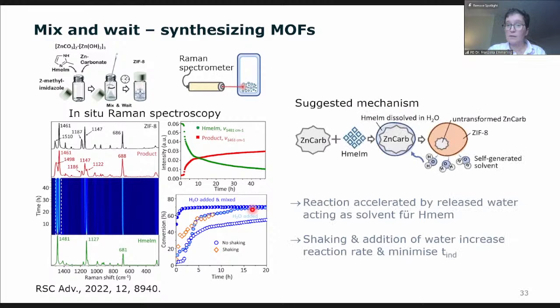And this is the mechanism we are suggesting in that case. So we start with our zinc carbonate. There is also water released during the reaction, and that dissolves our linker. And then we have a growing MOF material by reducing our zinc carbonate. And that's also the reason why we saw these white spots. So there's still some leftover material. So that was for us a nice reaction.